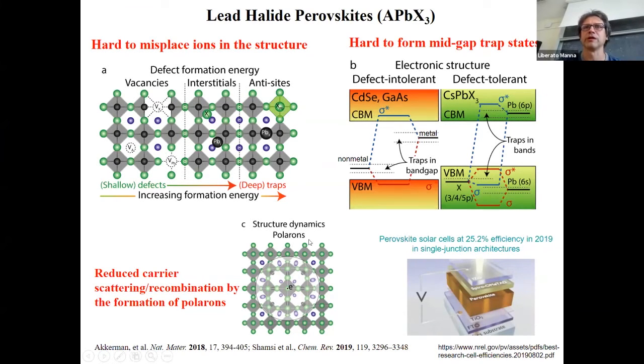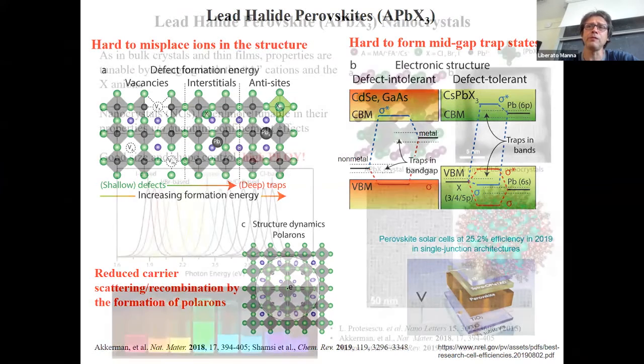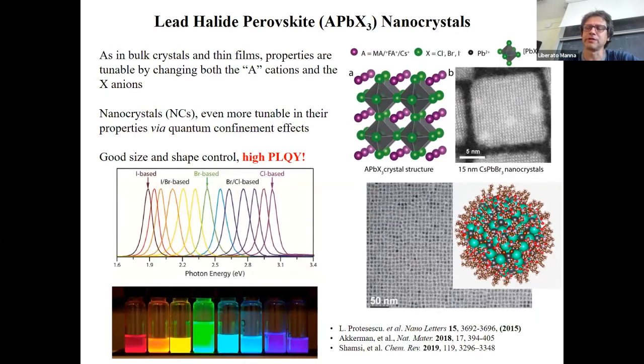But as you can see in panel B, contrary to traditional semiconductors, these vacancies, which form unsaturated bonds, lead to states which are nested in the valence and in the conduction band. So they're not so detrimental for the optical properties. Polarons are also forming in perovskites, which contribute to decreasing carrier-carrier scattering and long carrier lifetime, which is responsible for high photovoltaic efficiency in solar cells. You can change the optical properties of perovskites by changing, for example, the A cations and the X anion. And with nanocrystals, you can tune the sizes and also reach the quantum confinement regime in these materials.